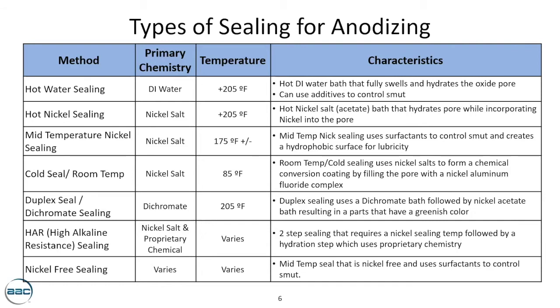Then the final process is nickel-free sealing. This is similar to your mid-temp nickel sealing. However, the primary difference is the active ingredient is not nickel, it's a different metal. This has become very popular for electrolytic sealing. Nickel discharge can obviously be costly and somewhat challenging if you have environmental regulations. So many customers who are doing clear or electrolytic coloring will use a non-nickel seal to seal their parts and ensure that they're still getting good quality as it relates to light fastness, but don't have to deal with the environmental issues associated with nickel.